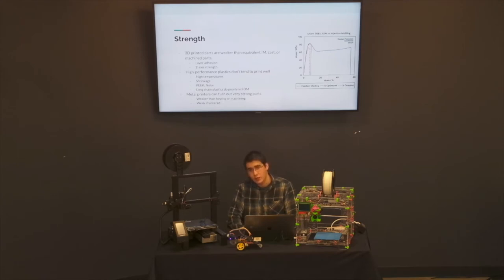Now, a compromise that a lot of people have run into with this is that high-performance plastics don't tend to 3D print well. There's a lot of aerospace plastics that are either high density or very strong, or they work well at high temperature, and most of them tend to be a real challenge to actually make come out of a 3D printer, if it's possible at all. Some common ones are polyether ether ketone. That's used in some aerospace applications as a substitute for aluminum. It needs things like a heated chamber, heated at 200 degrees centigrade.